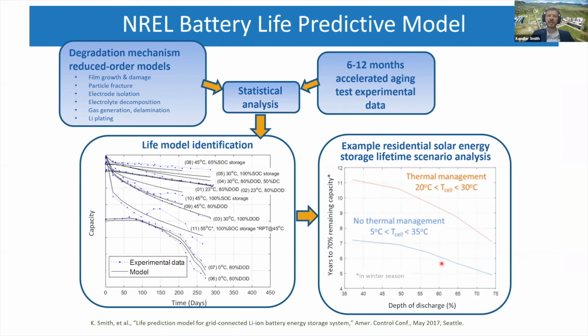And so here's an example of trade-offs. If a residential energy storage system had no thermal management, it might last 7 years if you cycled it at 50% depth of discharge, whereas if you added thermal management, you could get it to last 10.5 years at 50% depth of discharge. And then if you cycled to higher depths of discharge on a day-by-day basis, how long that particular battery would last.